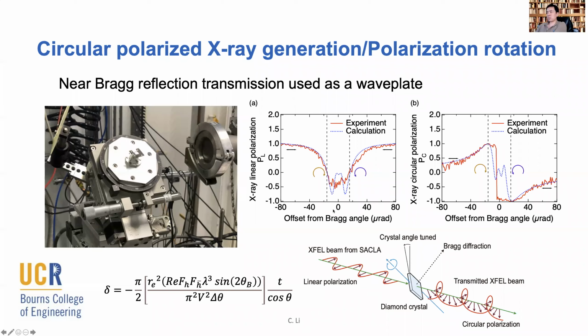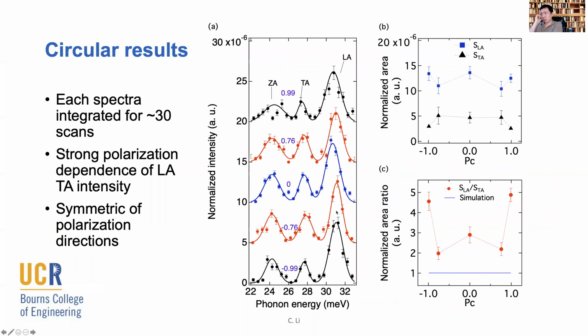So here are some preliminary results. Honestly, the statistics are still kind of bad, but I'm just trying to show it anyway. In the center, the blue line shows the beam that is completely in the non-circular polarized regime. On the top and at the bottom, we're showing two different degrees of circular polarization. Our hope is that the black curves on the top and bottom have the largest component of circular polarization, and the red curves show something intermediate.